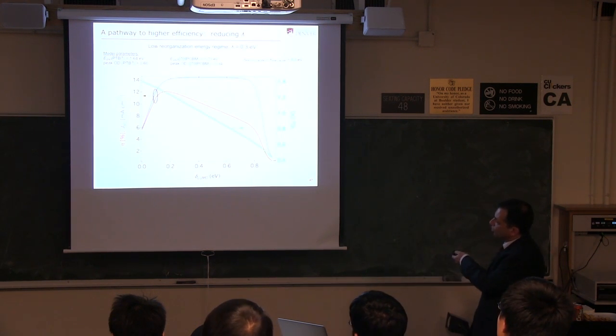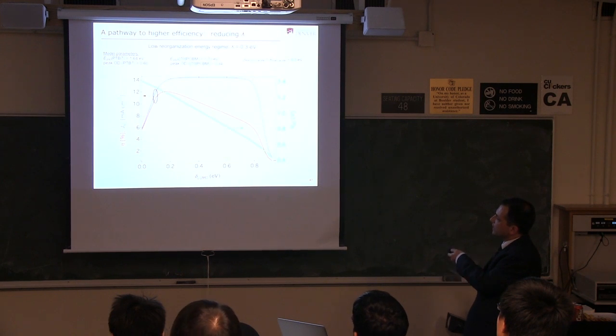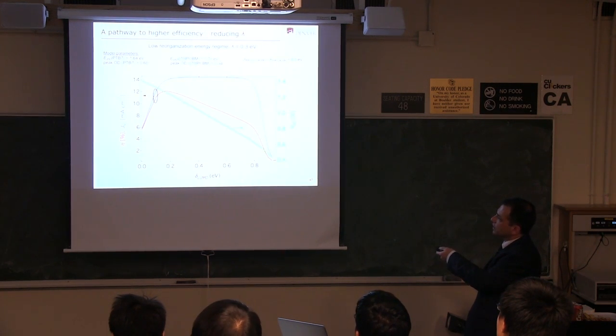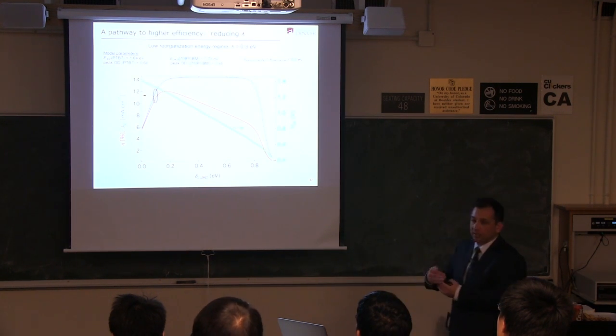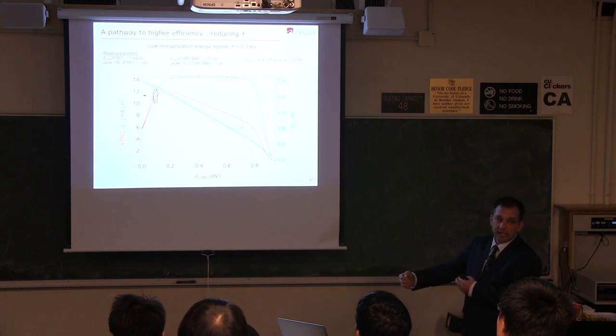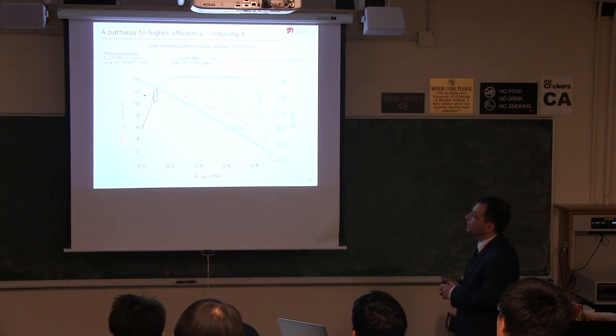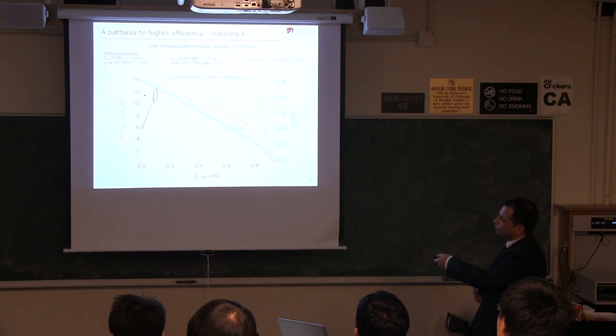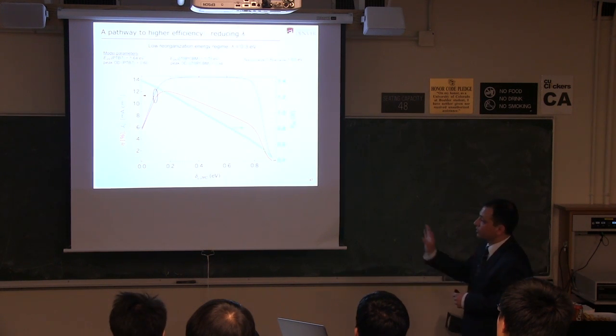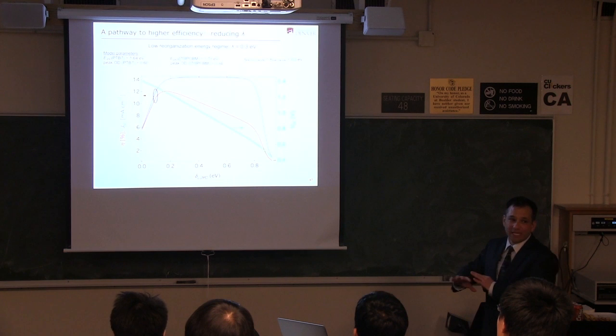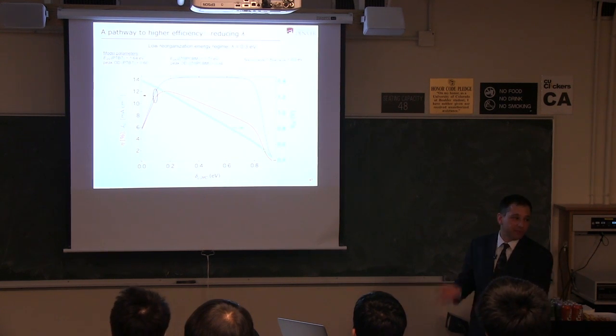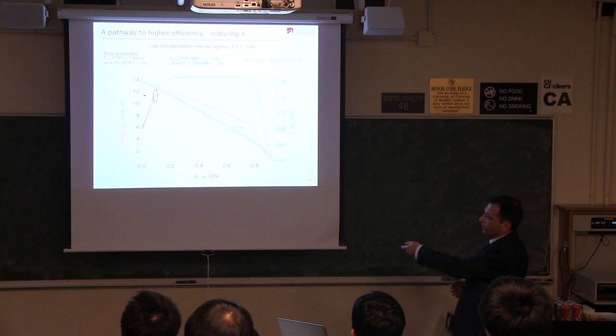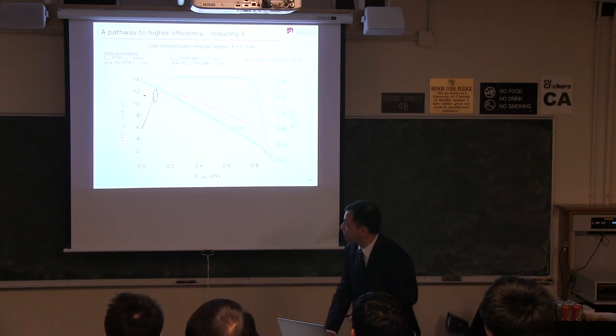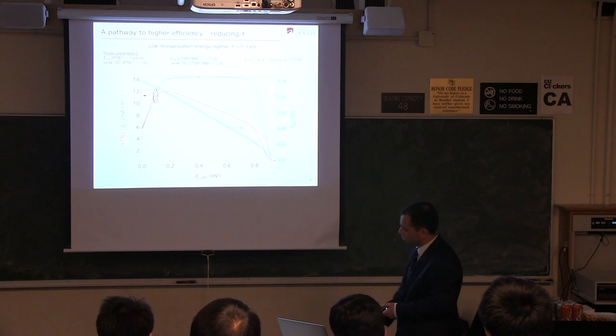That allows you to go lower on the delta LUMO and therefore go to higher voltage without losing current in the device before the current starts to drop off. Right? The current drops off because you're in the inverted regime of the Marcus theory, and the rate constant gets very low. Oh, by the way, according to this, the delta LUMO could get close to 0. In fact, it could go below 0. And that's saying that according to Marcus theory, you could suck up some of the thermal heat in the reservoir of the device, use that as an upconversion mechanism. In principle, that's allowed. You could run this as a thermal upconversion device. So anyhow, under that scheme, you get to about 12% efficiency.